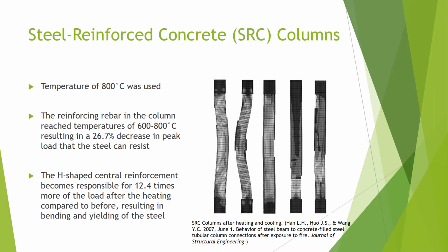The reinforcing rebar in the columns experienced a temperature of 600 to 800 degrees Celsius, resulting in a 26.7% decrease in peak load that the steel could resist. The H-shaped central reinforcement becomes responsible for 12.4 times more of the load after the heating compared to before. This results in bending and yielding of the steel.